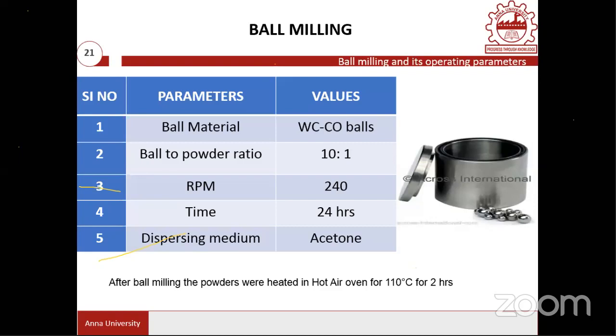Initially, in order to mix these powders uniformly and homogeneously, ball milling was used, and WC-cobalt tungsten carbide based balls were employed, and the ball to powder ratio was maintained at 10:1, and we milled every composition for 24 hours. During this milling, every half an hour, acetone was added, because the heat should not produce any other compound. So in order to have control over the heat generation, we also added acetone.